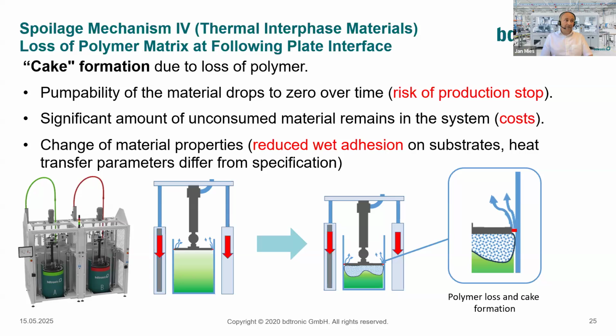And what you have is a kind of following plate which sits directly on the original container of your material supplier, and there's a tiny sealing element around. And if this sealing element is not properly aligned with the even wall of the container, or there's a small welding on the drum, it can happen that you lose polymer matrix over time. And that brings you in the situation that you form a certain cake underneath the following plate, which grows over time, and at a certain point you can't pump that material anymore out of your container.